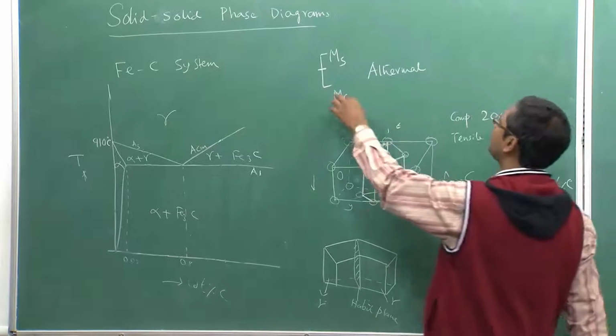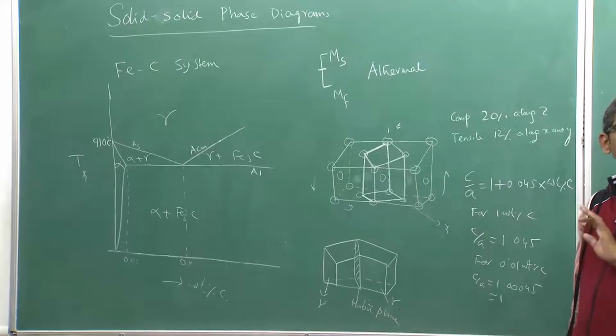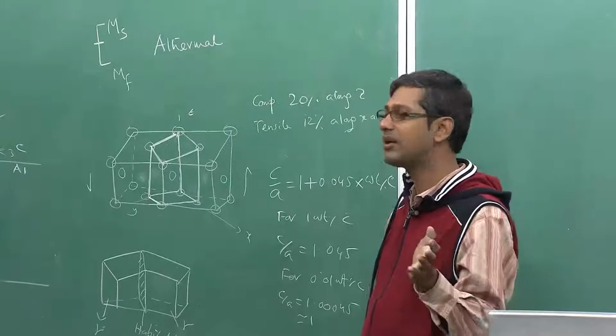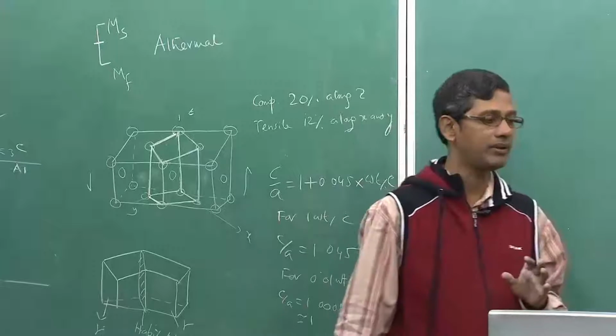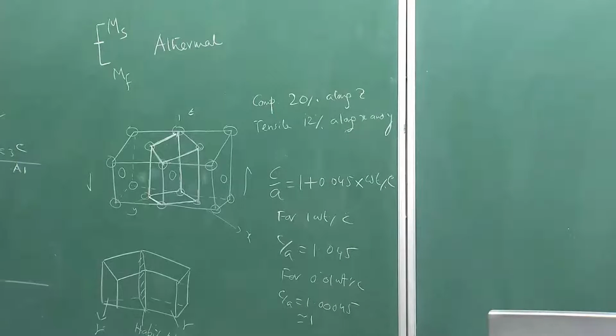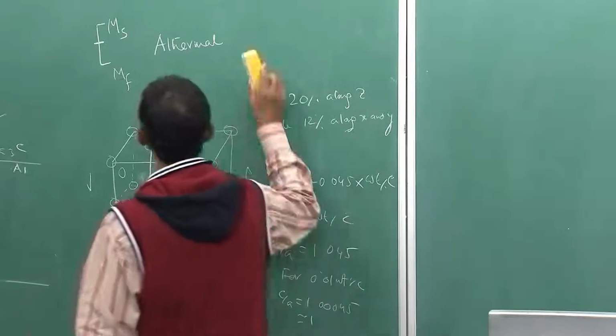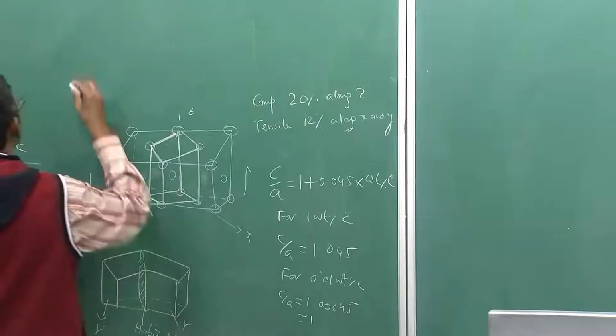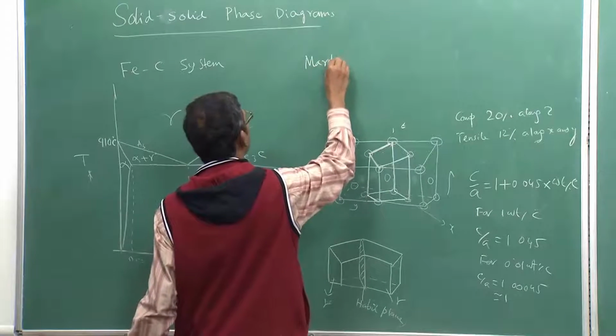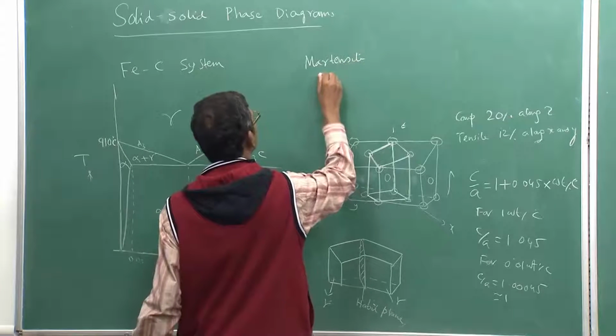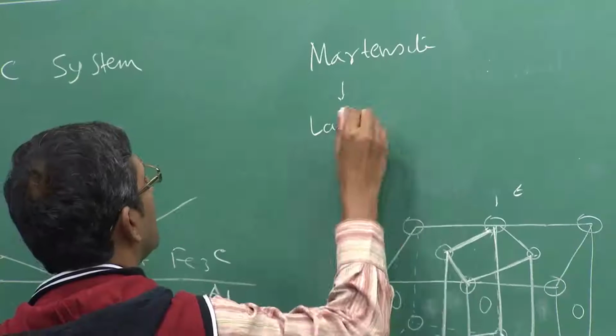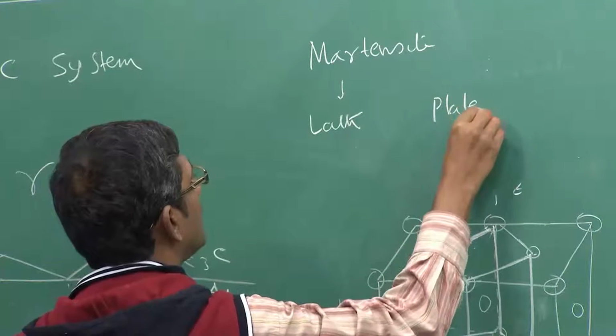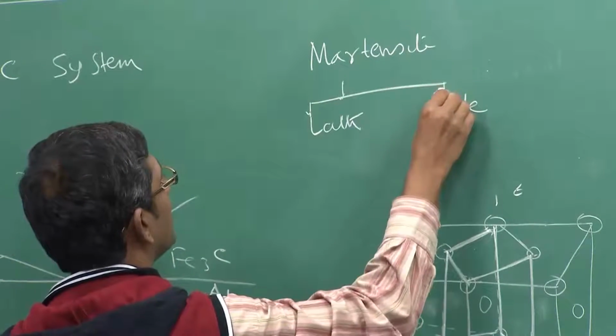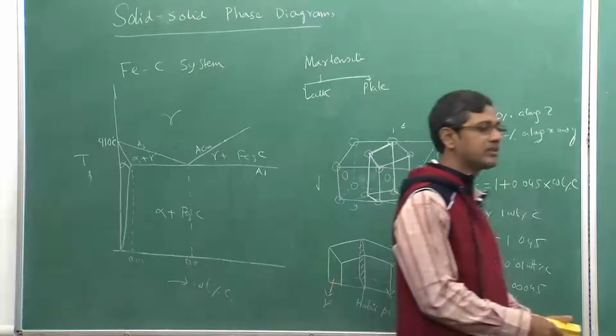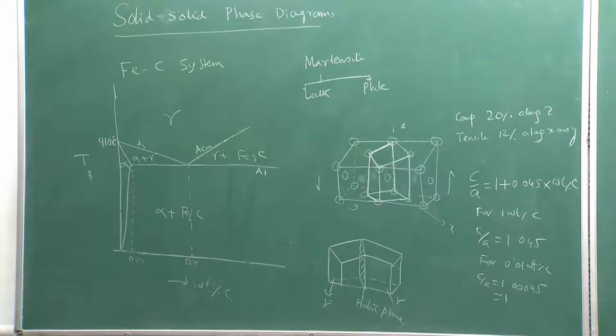And if you cool it down below MF, it should basically transform fully into martensite, all the gamma grains will transform into martensite, but that does not normally happen. That is one thing we should remember, we will discuss more on this. Last thing which I would like to tell you is that martensites have two morphologies. One is lath, the other one is plate. These are the two morphologies of martensite, and these morphologies will depend on what kind of steel you are looking at.